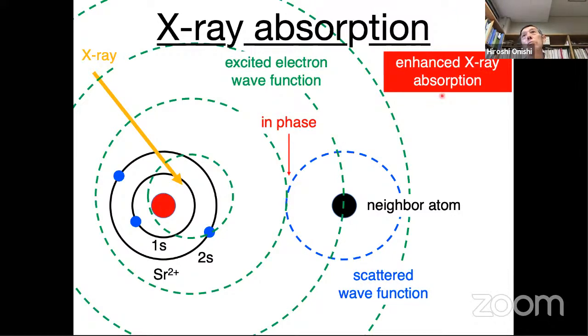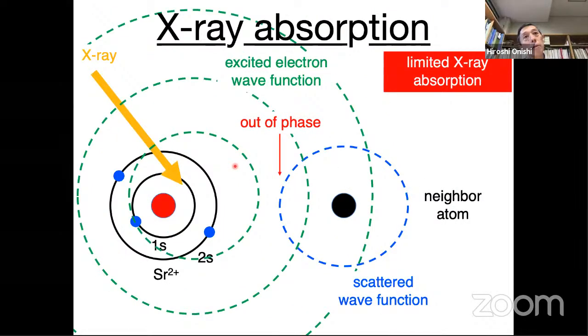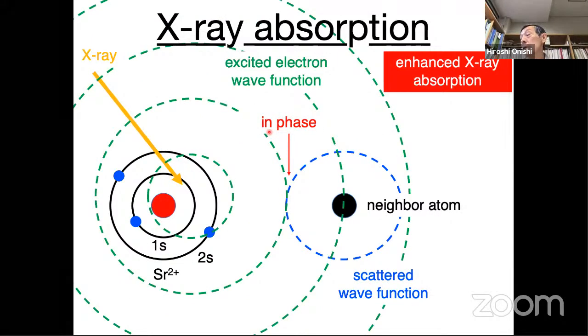So when this happens, the X-ray absorption coefficient is large. But when this doesn't happen, here the wavelength is different, so these two green and blue wave functions are out of phase. Here, X-ray absorption is limited. The important thing here is that out of phase or in phase is determined by the distance from the strontium cation to the neighboring atom. By using this phenomenon, I do not want to go into detail how to do so, but as a result, we get the distance from this strontium cation to the neighboring atom by observing X-ray absorption spectra.